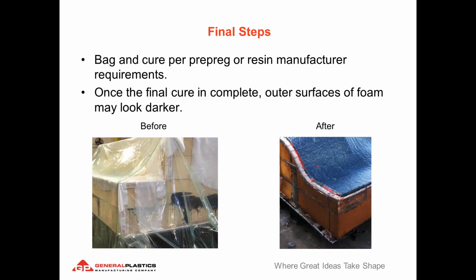So the final steps, we look at bagging, curing, and now we're ready to debag the product and look at the results. If we look at the before and after, even in an inert atmosphere autoclave, which of course is recommended in best practice for such large high temperatures and large amounts of organic material in the autoclave, we start out with a very cream colored material, and as we debag it, we reveal some oxidized foam surface. Within a couple millimeters below that surface, the foam is again back to its cream color, and it doesn't affect the properties. We've taken foam through multiple cycles and have not seen any decay or surface degradation. However, that's with an inert atmosphere and properly vacuum bagged and sealed.